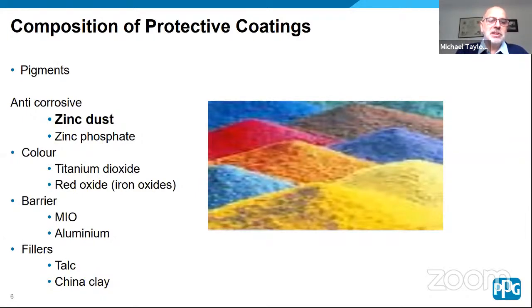In terms of other pigments that we use, there's coloured pigments like titanium dioxide, the most used pigment in the coating industry in terms of colour. Red oxides, so red iron oxide, yellow oxide, carbon black. Some of these are organic pigments, some of them are inorganic pigments. Organic pigments tend not to have the same colour durability as inorganic pigments, but the inorganic ones tend to be